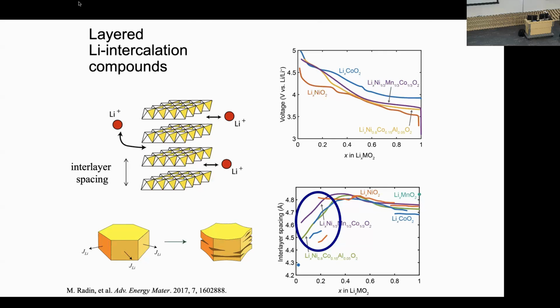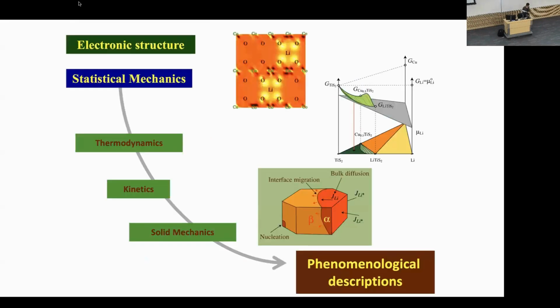So you build up these large stresses, and that causes kind of the equivalent of mud cracking, this fracturing where these sheets might cleave, and you create other kinds of cracks. And so that's a problem. In actual batteries, you typically stop. You don't pull out all the lithium. So you lose this extra capacity, because you want to be able to cycle as much lithium as you can, because of these chemomechanical issues that happen at the high states of charge. So that's another challenge to overcome, to overcome these drastic shape changes that cause fracture.